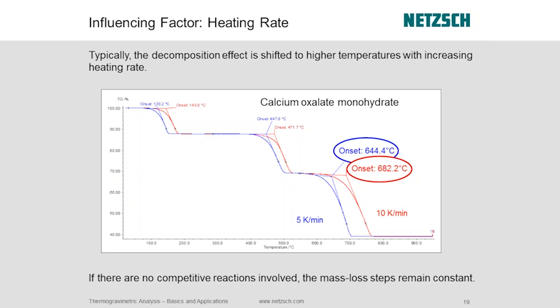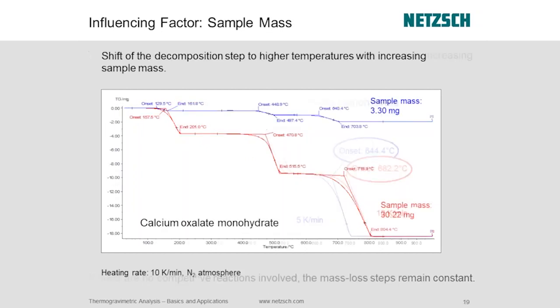But when you go to a higher heating rate, then you create a larger thermal gradient in the sample. Okay, and that means it takes longer for the sample to reach these reaction temperatures. That's why it's being shifted. So that's a point I wanted to make about that as well. All right, so again, the temperature distribution of the sample. We talked a little bit about that in the beginning. Those are, again, more important things for you to remember. And you're going to have that same kind of issue with sample mass. Okay, the bigger the mass, usually the longer it's going to take for the heat to transfer into the material. So you get a shift then in terms of those temperatures.